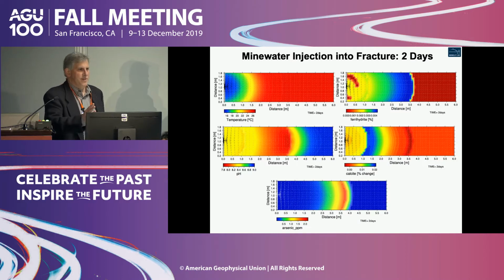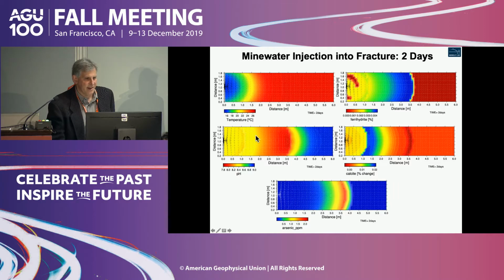So we just run some simulations, because it's nice to just run them and see what happens, to have as much possibility to get different behavior. And we did get a lot of very interesting behavior in this simulation. So for example, you can see the temperature here. It's about 15 and about 30 degrees here. And you see the pH after 2 days starting to get quite a bit of variation. You get a very low pH band up in here, somewhat higher here. It's starting out in the 8s or so.